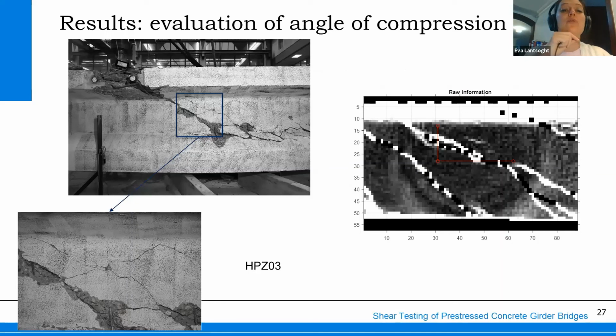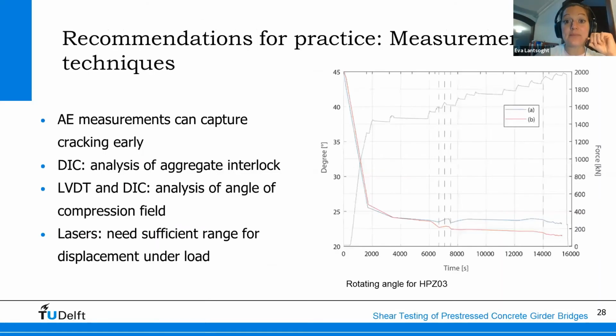One thing that we've been able to analyze further with the digital image correlation analysis is the angle of the compression field. So here you see some of the analysis that is done. And on this graph, you see the angle of the compression field as a function of time. And here, for comparison, you see the loading graph. So this is really after all the cycles of loading, this is until failure. And what we see really is how the angle rotates downwards, right? We start at 45 degrees and then it rotates downward and downward and downward until we are at about 22 degrees.